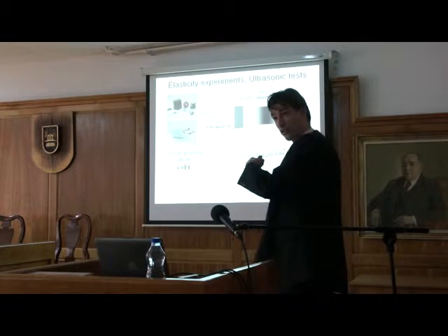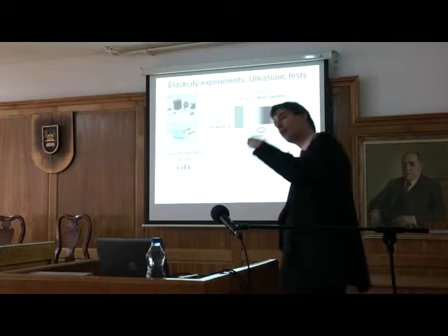You again think in terms of an engineer or mechanician. If you have a wavelength like this, it means you have here a high stress, a low stress, for example. So it's a structural test, and the material which you test is smaller than the structure. So the material is like this, because the material has to feel a homogeneous boundary. So the material you test with a wavelength of some length is the material which is 1 order of magnitude, practically speaking factor 5, 6, smaller than the wavelength. You don't test the material at the size of the wavelength, but at a smaller size.